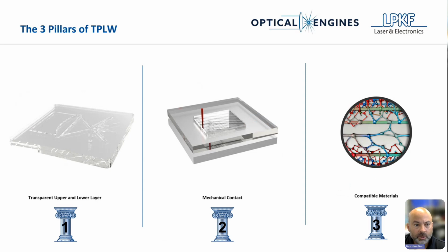Jumping into the 3 pillars of transparent polymer laser welding. The first one: both the upper and the lower layers of the bonding partners are transparent. They can be optically transparent or IR transparent. More specifically, optically transparent, because some of the IR transparent materials, let's take, for example, nylon, in their natural state are somewhat milky or chalky colored or almost opaque. And so the 2 micron doesn't work very well with those specific materials. So try to say both the upper and the lower layers optically clear is probably the best case for this.